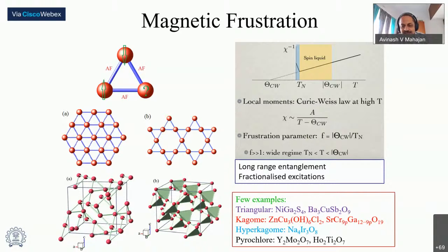Okay, but clearly, again, anecdotally and just based on thumb rule, a frustration parameter of 5 or 10 is not so significant because it doesn't allow you much range where you explore the spin liquid behavior. On the other hand, if it is much larger, like 100, or if you don't even see ordering, then that is quite significant. Then over the years, theorists told us, oh, this is actually an entangled state. You should also see fractionalized excitation.